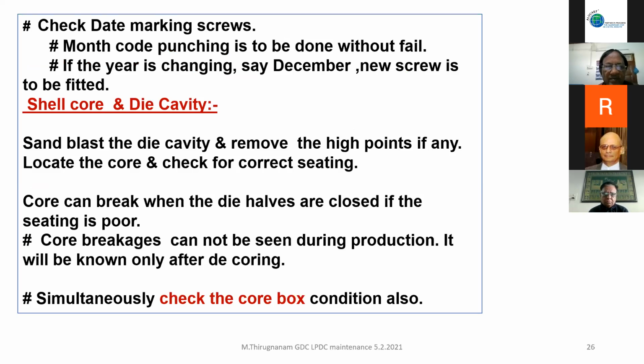Now let us move on to shell core and die cavity. Sometimes you will be locating a lot of shell cores on the die cavity, and the important thing is that the shell core can grow. If the shell core die halves are not closing well, all the core pin diameters will expand by 0.2, 0.3. What will happen is it will not sit well on the top core, and when the top die half comes and sits on it, the core can break also. So you must see that the core pin areas are kept very clean and the dimensions are maintained.